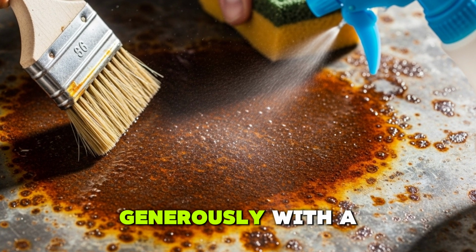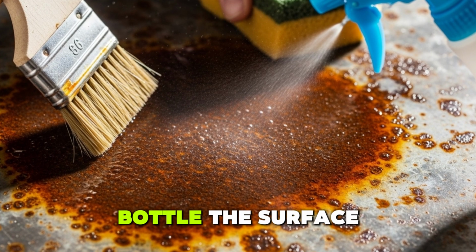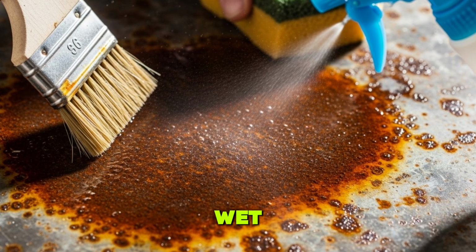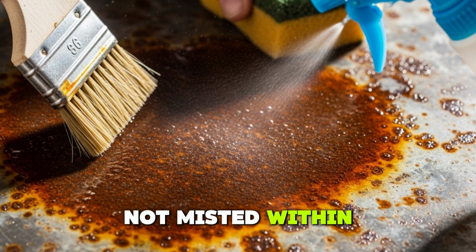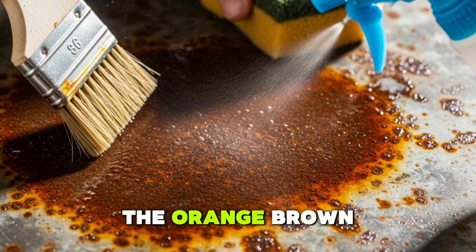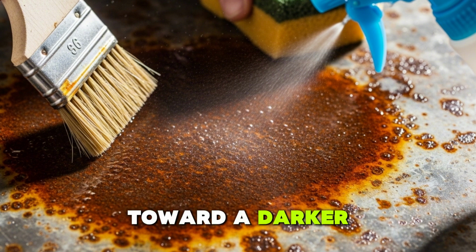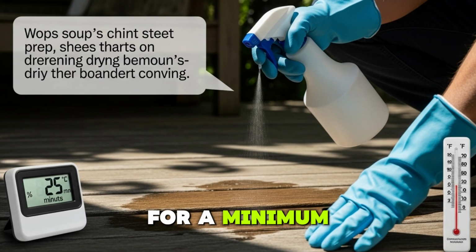Apply the solution generously with a brush, sponge, or spray bottle. The surface should be visibly wet, not misted. Within 3 to 5 minutes, you will see the orange-brown rust begin shifting toward a darker tone. This is the conversion reaction beginning. Leave the solution in contact with the surface for a minimum of 20 minutes, maximum 30. Do not let it dry prematurely in direct sunlight or high heat.